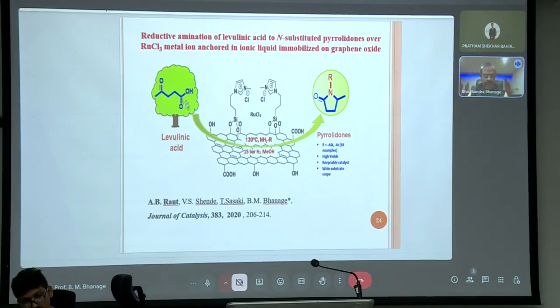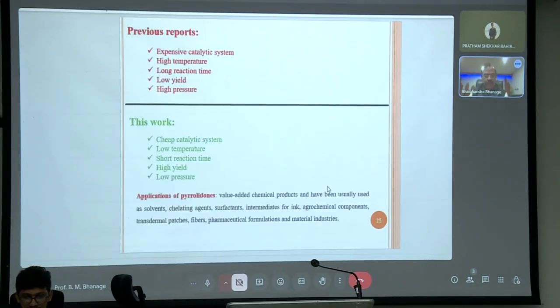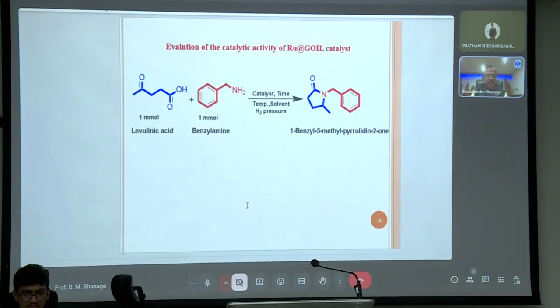And you take levulinic acid and a primary amine and 15 bar of hydrogen in methanol at 130 degrees centigrade, you will get a reductive amination reaction because this ketonic group will form an imine with the primary amine and eventually it gets cyclized to give you pyrrolidones. So these pyrrolidones find applications as solvents, chelating agents, surfactants, intermediates for ink, agrochemical components. It is used in transdermal patches, fibers and pharmaceutical formulations for material industries. So this is the reaction.